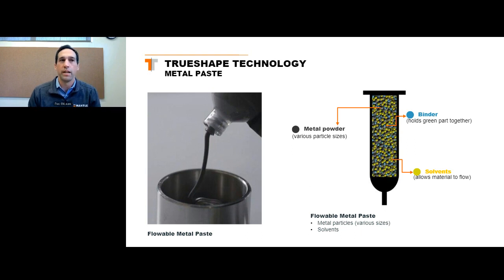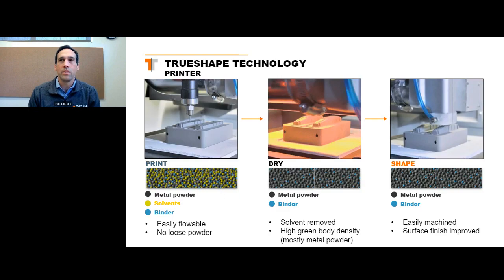We extrude this paste, and then as we print, as we extrude, after each layer, we heat and we dry the paste, and that removes the liquid. And so you're left with the metal powders, the metal particles, and a little bit of glue or binder that holds everything together. And at this point, it has the consistency of, let's say, a dense foam or a crayon. So it's no longer in the liquid state. It's stable enough to hold the shape of what's been printed.